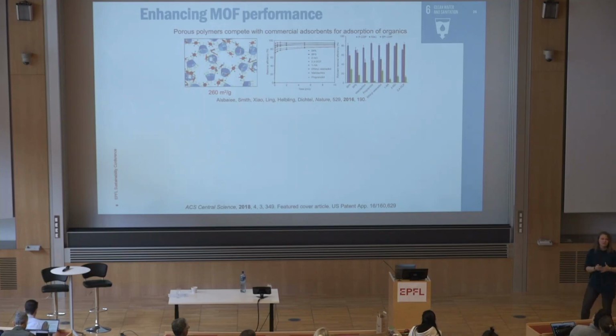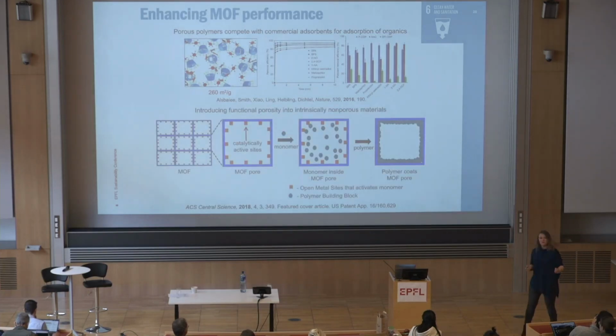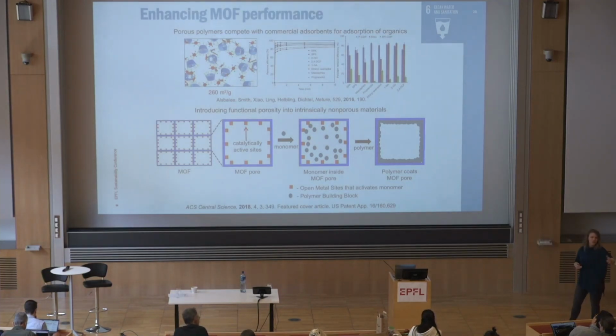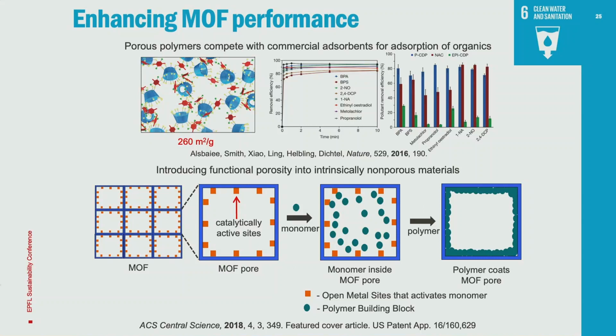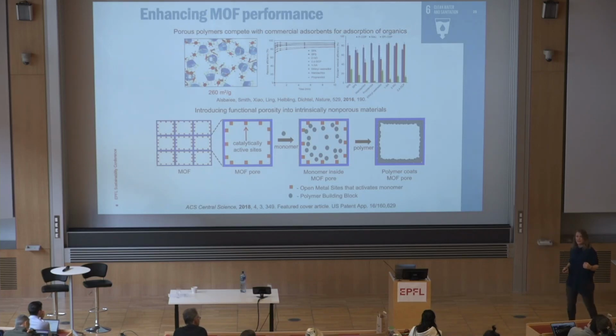I thought, well, I've already told you that MOFs are permanently porous, okay? So what we decided to simply do is use our MOFs as a template, so to speak, where we grow polymers inside the pores. So basically what we're doing is we put a monomer inside, those monomers cross-link, form long polymer chains, and they get stuck inside the materials, kind of like a ship in a bottle, if you've ever seen one of those, okay? So then anything that gains access to the inside of the MOF can now gain access to the polymer, which has nice functionality on its backbone that can really bind these metals. It's not very easy to make polymers that are highly porous because they're not very rigid, okay? And that's kind of the point behind this.